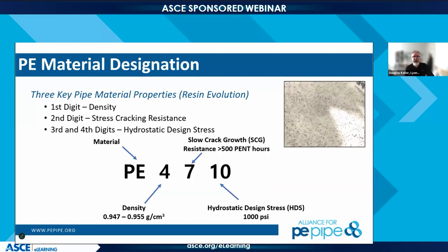So when Alan talks about the tensile stress, that tensile stress, when we run a tensile test, is basically applied over several minutes, maybe 3-4 minutes, 10 minutes at the most. And so when you're applying a stress over a short time, you get a much higher value. This 10 is basically our 50-year value. 50 years is kind of arbitrary. It doesn't mean the pipe fails at 50.1. It's just a point in time that we basically look at an intercept.